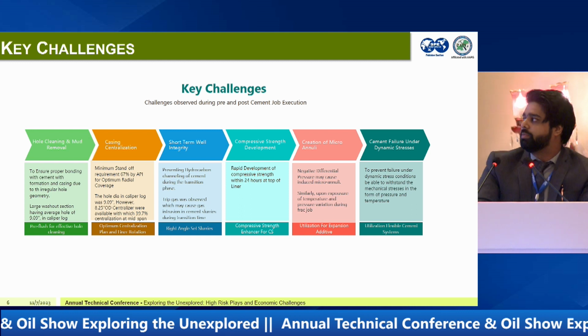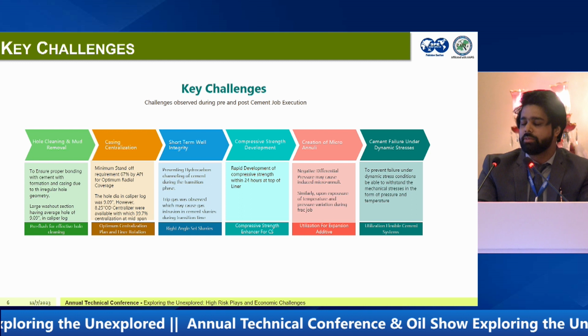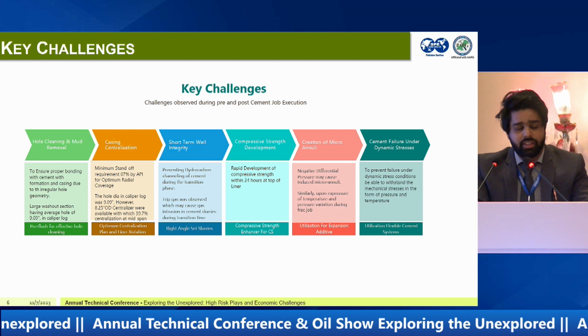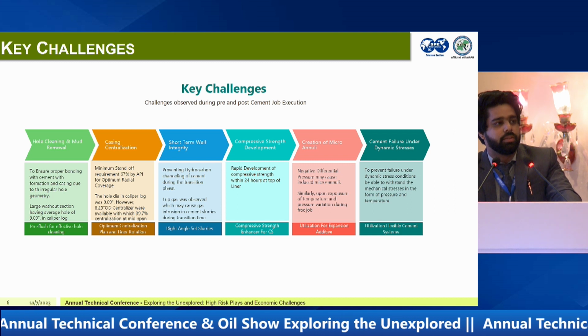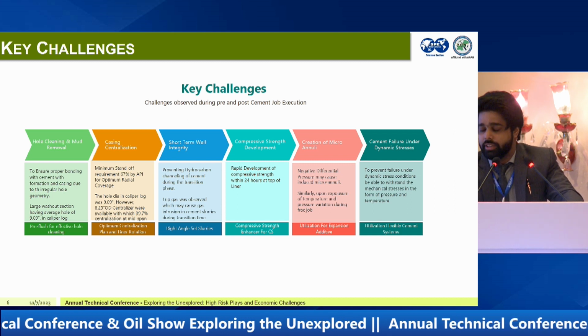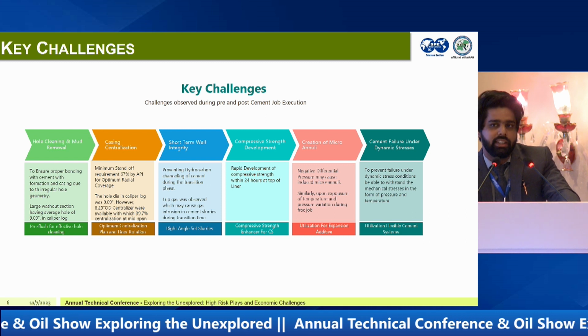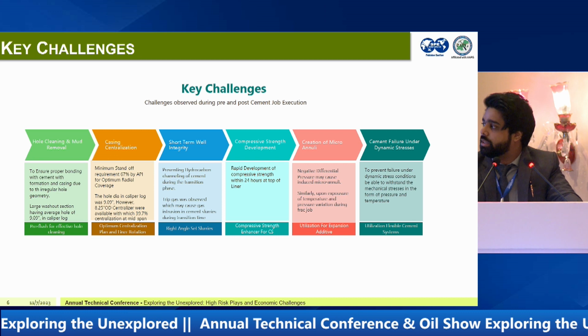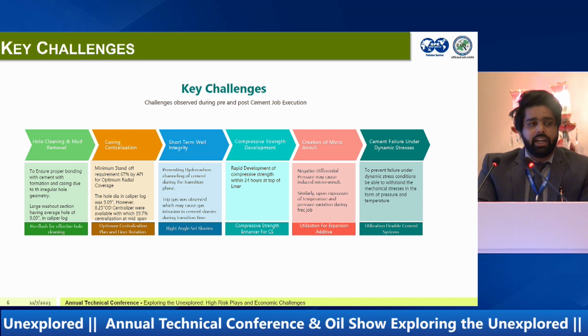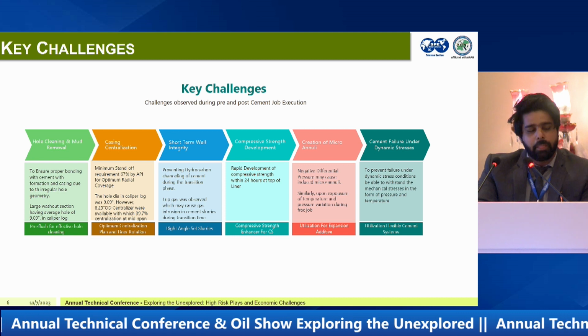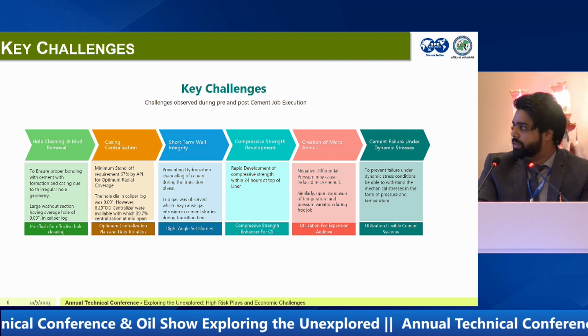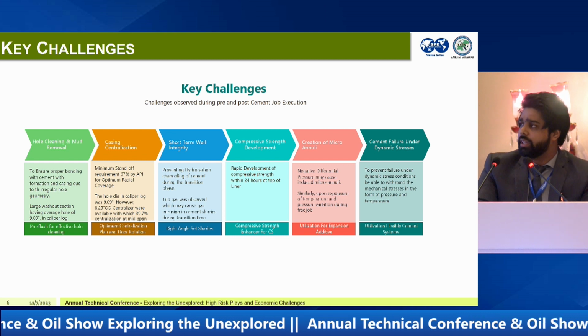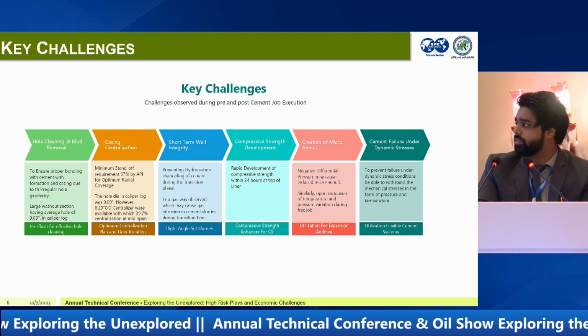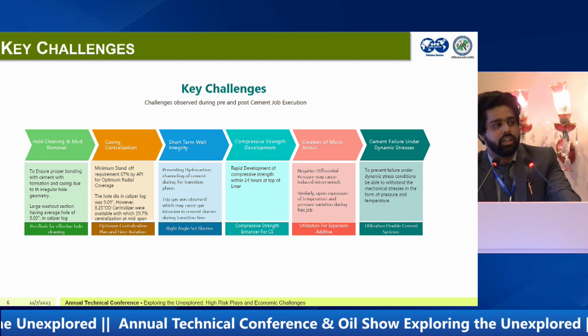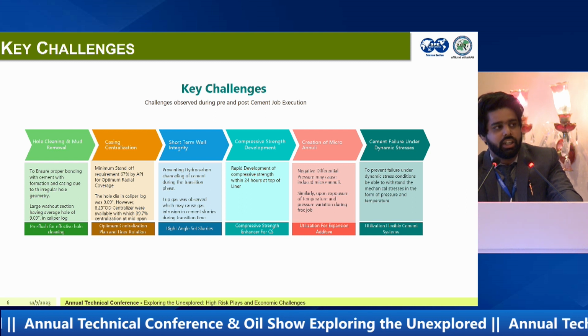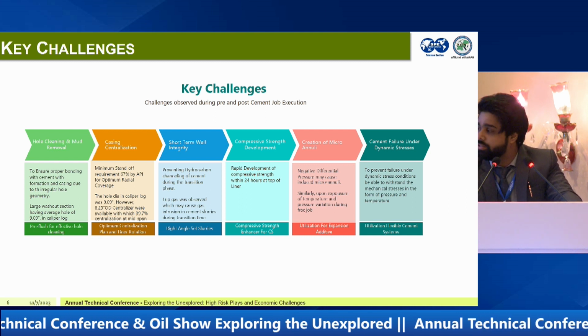Then we had a challenge of short-term integrity, like preventing gas migration during the transition phase, as we had trip gases observed during the tripping operation. For this purpose, we incorporated right angle set slurries, which have a low transition time from 30 to 70 Bc. Then we had a requirement for compressive strength development, which should be rapid within 24 hours at the top of liners. To enhance this, we incorporated a compressive strength enhancer like microsilica, and we achieved the desired compressive strength.